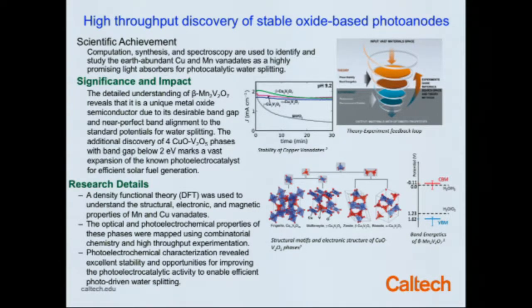Some of the results have been materials like copper and vanadium oxide, copper vanadate, in a number of phases that were only known to geologists before. In fact, they have geology-sounding names like fingerite, mcbirneyite, ziesite, and blossite. Now we can know them to be useful electrochemical materials because they have appropriate band gaps and their band edges straddle the water oxidation and water reduction levels. So we can transfer charges from the conduction band to the catalyst efficiently, both on the water oxidation and water reduction side.